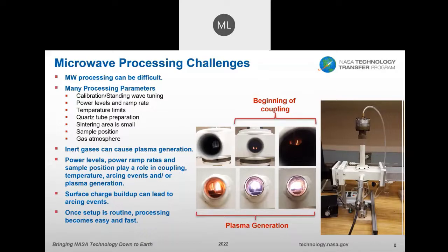Another problem is sometimes the inert gases, if the power is added very fast or quickly, or depending on the material that's in there, you can generate plasma. Surface charge can also happen depending on constituents in the fiber, or in whatever it is you're sintering, or just the cavity where your charge is building up within the cavity of the microwave, and you could have arcing events. Okay, next slide.